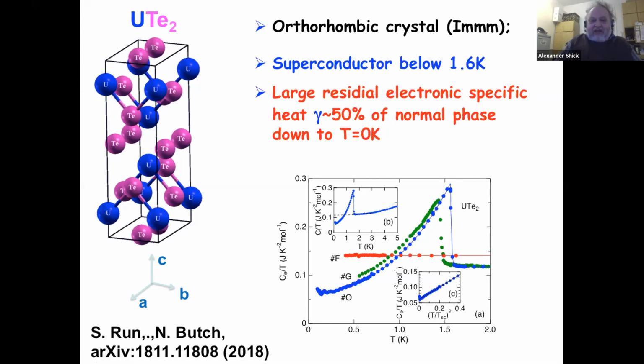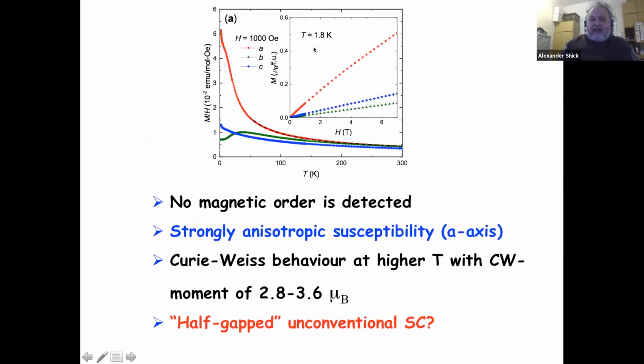And people started to investigate the magnetic properties. It is a paramagnet, but it has very strong anisotropic magnetic susceptibility. You see, it is shown here. Along A, it is much higher than along the B and C axes. At the higher temperatures, they estimated the magnetic moment around 3 μB, and especially due to this unusual behavior of the specific heat, there were many proposals that it is a half-gapped unconventional superconductor.